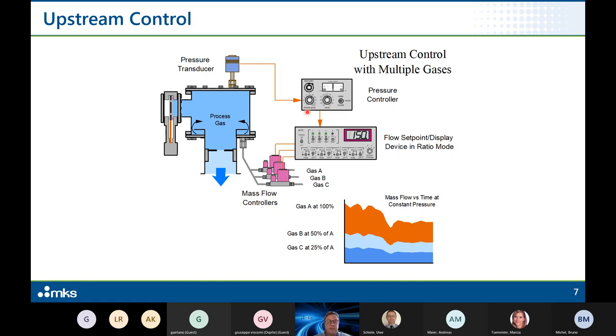The downside is that you give up control of the total flow. So you could set up a ratio control, which means that the composition of all gases injected to the process will not be changed, but we need to change the total flow to adjust the pressure. So you have one parameter less to optimize your process, and depending on the size of the substrate and the geometry of your process, this could lead to inhomogeneity of the deposition.